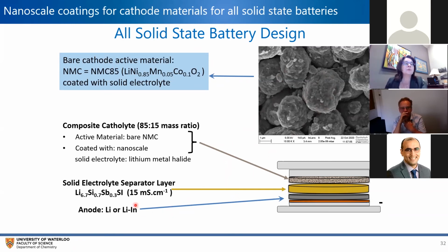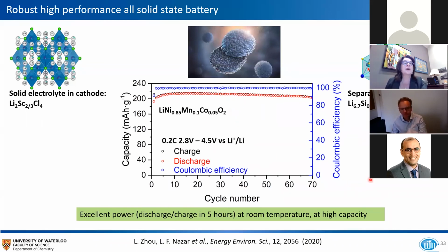So in this cell, we use the argyrodite that I mentioned 3 slides previous, which has this conductivity of 15 millisiemens, and we use that material as our separator, and we use the halide as the electrolyte in the catholyte along with this positive electrode material. And typically we have about 85 to 15 mass ratio of the cathode to the electrolyte, and we use a typical lithium or lithium indium as our negative electrode. So we construct these cells, of course, in our lab and subject them to a little pressure to get them to work well, and work well they do.